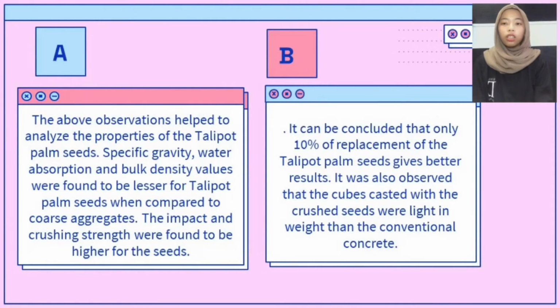For the discussion, all the above observations help to analyze the properties of the Talipot palm seed as given in the previous data. The specific gravity is lesser for Talipot palm seed when compared to coarse aggregates. It also follows that water absorption and bulk density are lesser. The impact and crushing strength were found to be higher for the seeds. It can be concluded that only 10% replacement of the Talipot palm seeds gives better results. It was also observed that the cubes casted with the crushed seeds were lighter in weight than the conventional concrete.